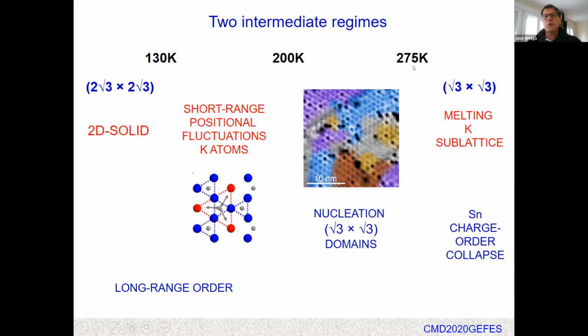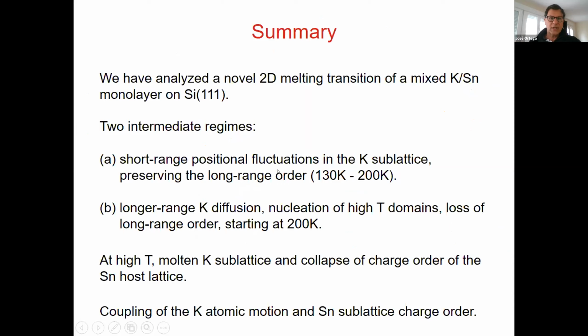And finally, above close to room temperature, above 275 Kelvin, we have the complete melting of the potassium sublattice and the complete collapse of the tin charge order. And I think I can put the summary. So in summary, we have analyzed a novel two-dimensional melting transition for a mixed